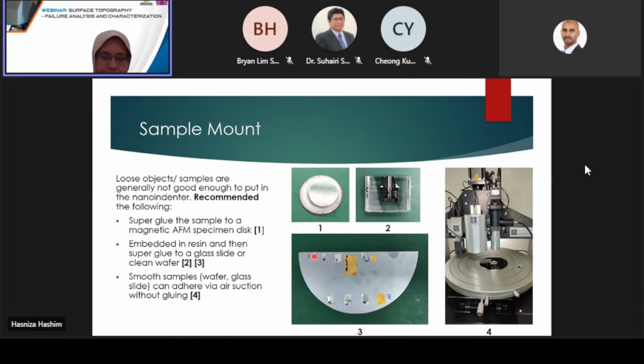There are several ways to mount the samples. We can mount the sample onto a magnetic AFM specimen disc as here, and then put it on our magnetic sample stage, or we can use the suction ring to hold a very smooth sample like a glass slide or clean wafer. If you have flexible or odd-shaped samples like bone or fiber, you probably need to embed them in some resin or epoxy and do the cross-section and polish the surface down as shown here.